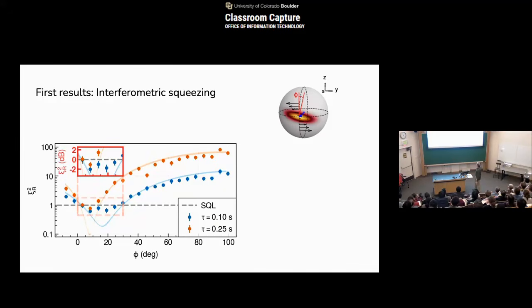And then we can try to measure the squeezing. Here, this is how wide your ellipse is as a function of angle. So it gets wider a lot. It doesn't get very much narrower yet. But we are still limited heavily here by some classical noise, because as you know, it's already hard to do a quantum limited measurement, but now we want to see 10 to 20 dB squeezing, so we have to measure even much more precisely, and so we are learning a lot. But we believe that the states we are creating, everything points to them already having 10 to 20 dB squeezing, but we cannot show this yet.